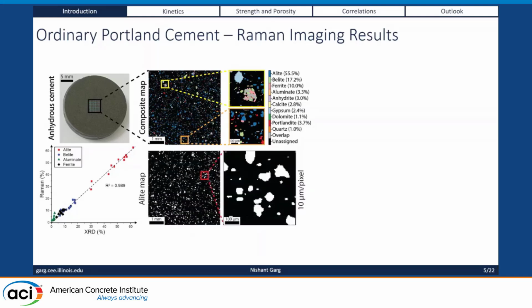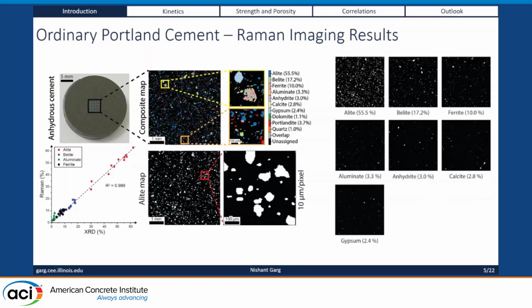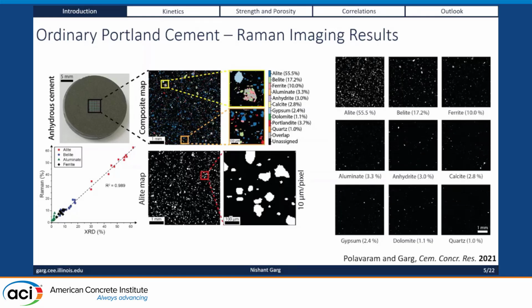And we can then start to obtain these very interesting phase-specific maps, right? So if you look at this here, you have now the alite map. So this is a zoomed-in version on the right here. You can start to see the individual alite grains in the system, right? So it's kind of like looking at a Google map, and you're zooming in to that specific location. And then you can obtain all these different maps for all individual phases, even down to something like quartz, which is at the order of 1%, and you can quantify it, okay?